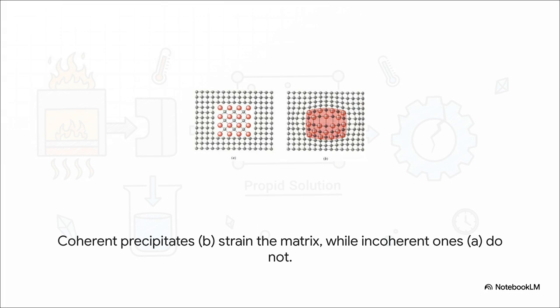And this slide, wow, this shows you perfectly why that strain is so important. Look at the image on the right. That's a coherent precipitate. See how it's warping and distorting that nice, neat atomic grid around it? That distortion acts like a microscopic roadblock. So when the material is under stress, tiny defects called dislocations try to move through it, but they get blocked by these strained areas. That makes the material way, way stronger.